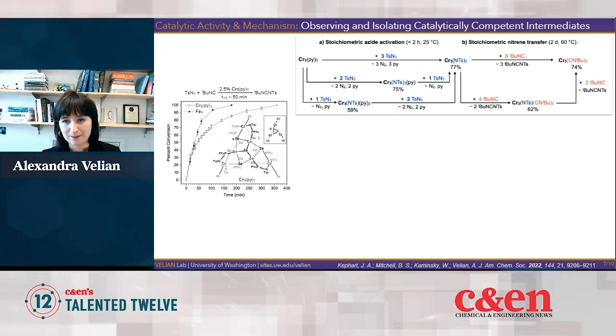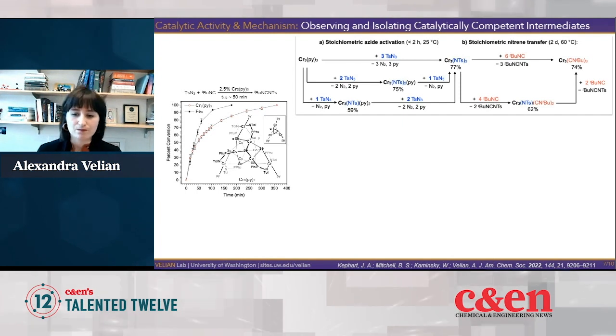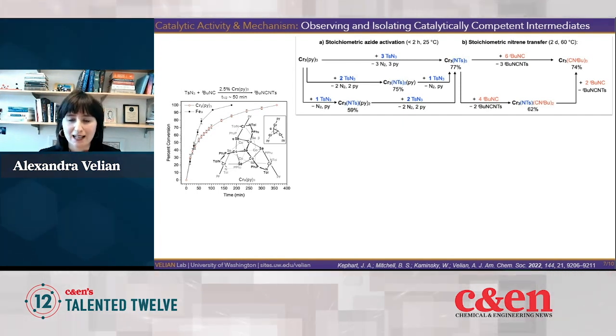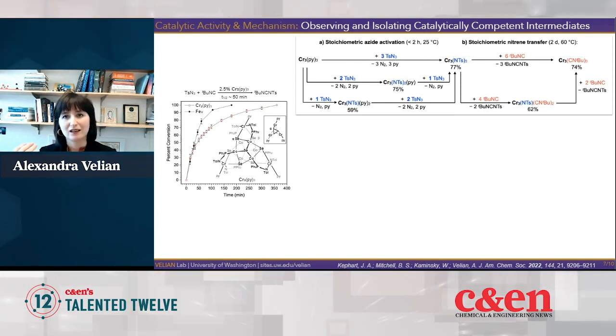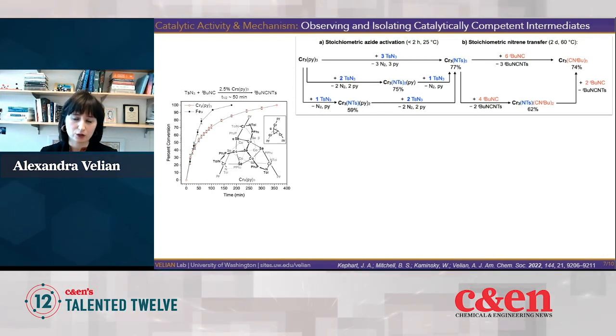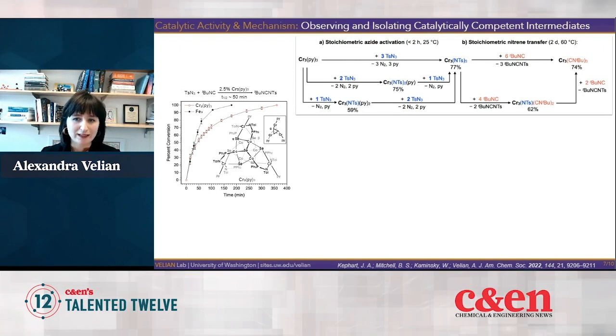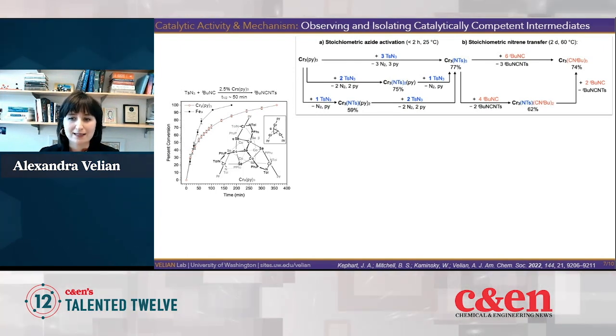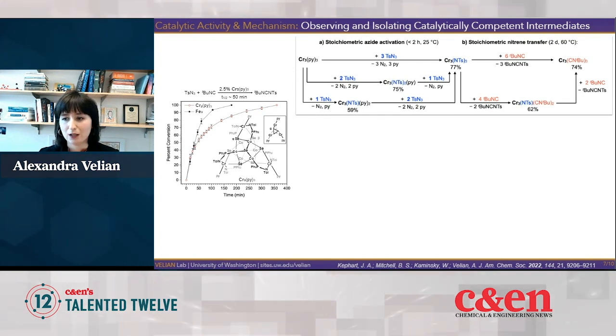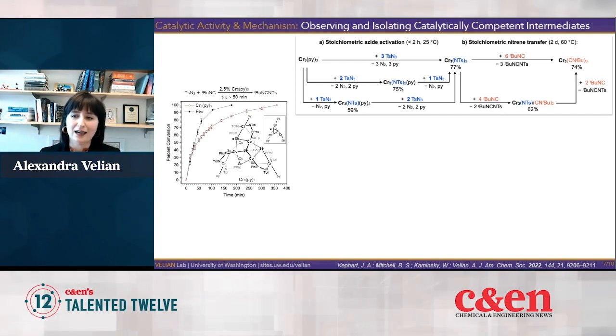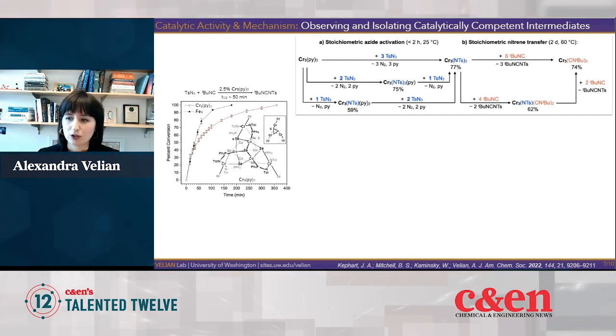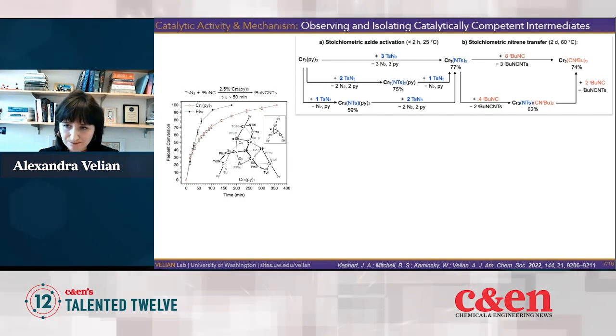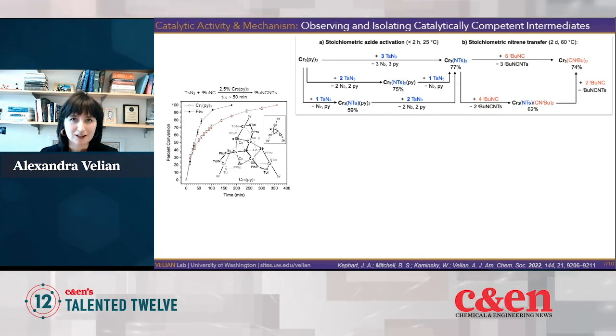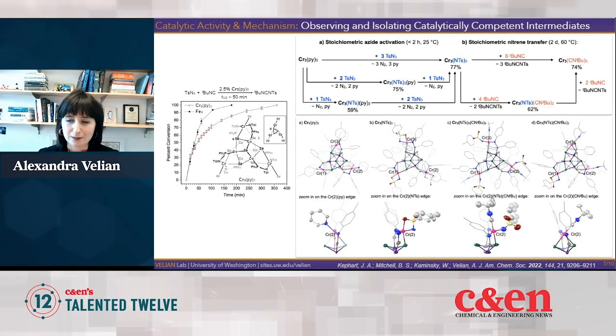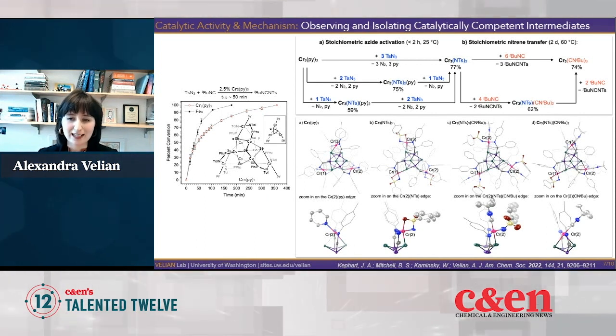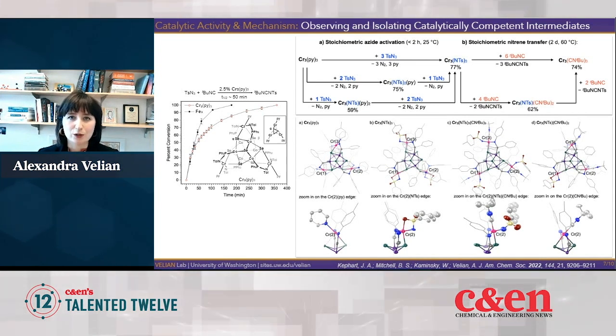to facilitate this transformation. So in stoichiometric conditions, John Kephart, who led this research project, found that he can actually isolate all the key catalytically competent intermediates within this transformation. So treating the cluster with 1, 2, and 3 azide equivalents provides these intermediates, which can be isolated and studied in great detail, and then sequentially we can add isocyanide to transfer the nitrene, revealing the original chromium 2 sites on the cluster surface. And so single crystal diffraction is really a fantastic way to gain these atomistic insights into the clusters, and it enabled us to get almost a frame-by-frame movie of how the transformation occurs at the single edge site.